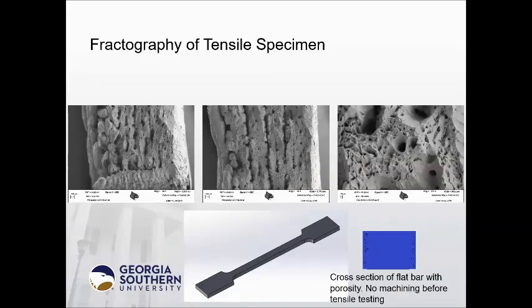And these are some SEM pictures of the fracture surface. As you can see the layers, it's very obvious to distinguish the layers of each layer print, and also you can see there are some gaps between the contouring and the infill region. And the included porosity is mostly located near the subsurface after 3D printing, and these defects can lower the ductility and reduce the tensile strength of the part.